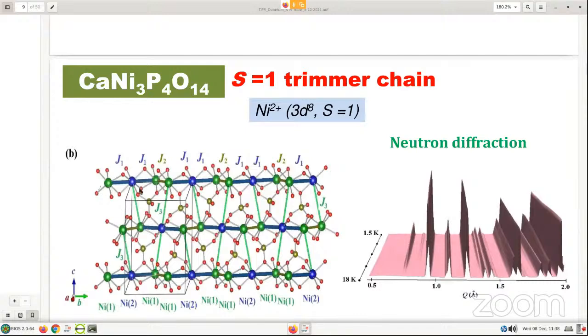As you can see, the crystal structure has been derived by doing the neutron diffraction experiment and analysis. And of course, the magnetic atoms here, there are 2 magnetic sites, nickel 1 and nickel 2. Basically it is J1, J2 kind of interaction along the chain. And the question here would be, what is the interchain exchange interaction? Throughout the journey, I will show that in fact, for this system, the J3, which is the coupling between 2 chains, is not negligible, and that's why it almost shows a 3D kind of behavior. Here we are talking about nickel 2+ with 3d8 state, with spin equal to 1, the spin 1 trimer chain we are talking about.